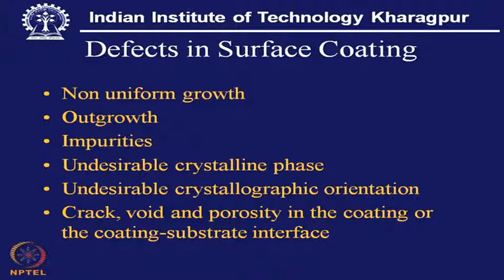Then we have, this is also very important to see, that this is a coating, but coating does not mean only its composition, stoichiometry and like that. There are certain crystallographic planes one likes to have parallel to the substrate surface in order to enhance certain property and in order to avoid certain weakness. So, in a coating what we like to do? To minimize this weakness, limitation and to increase its strength.